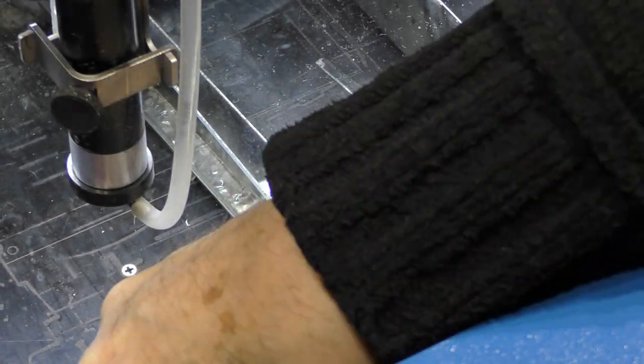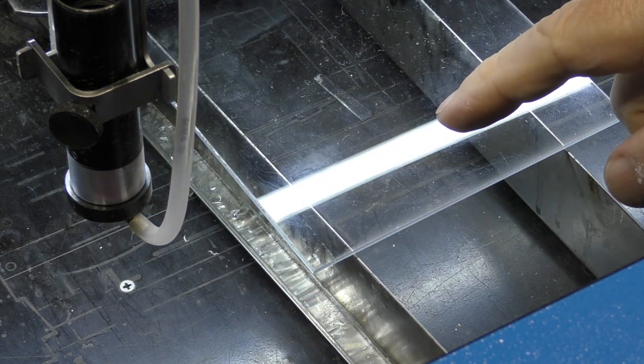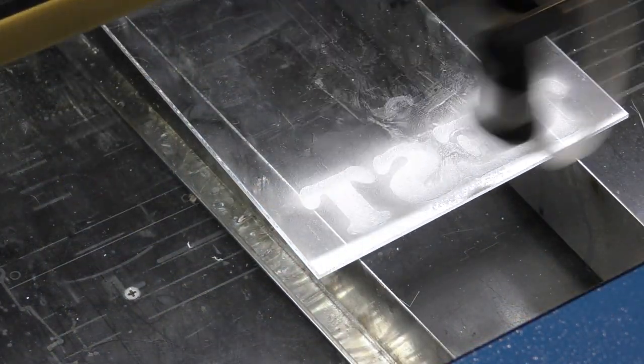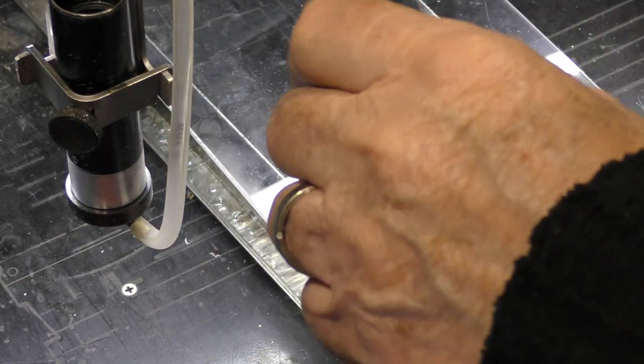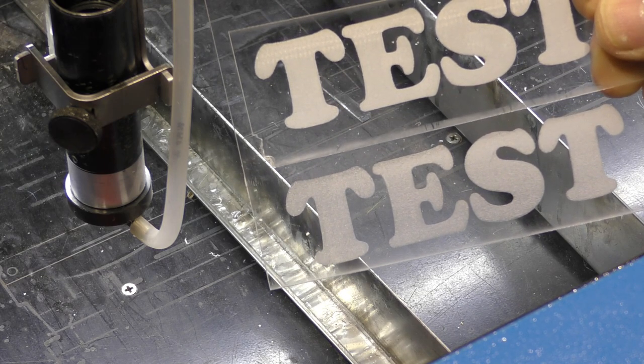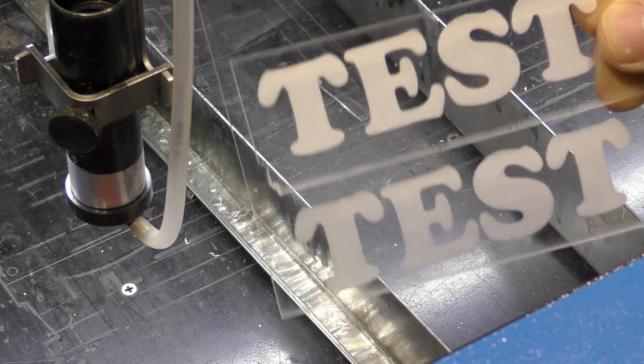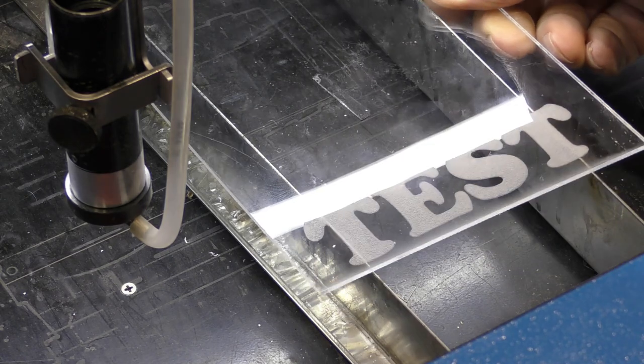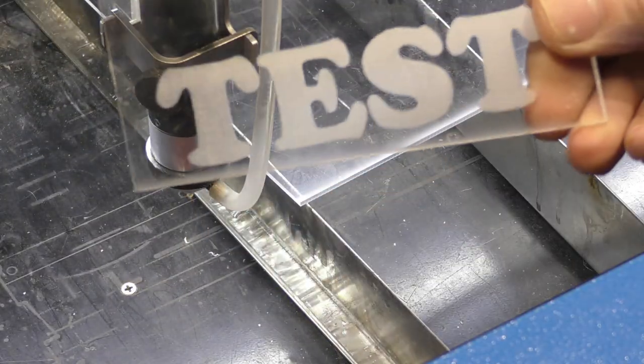Now while I'm here in the workshop I might as well do one more test. And what I've done I've now set this up to a 12mm gap. One millimeter above the nominal focal point for this lens. So that's a lot for a very short focus lens. Okay now again I'll just demonstrate to you how unimportant this dust is because look I can just wipe it off. It's dust. When we compare that with our previous one there is no comparison. So it's pretty critical to get the energy density at the surface spot on. To get those bubbles rather than melting or evaporation. I think that what we've got here is melting now rather than bubbles. So I'll just cut that off.